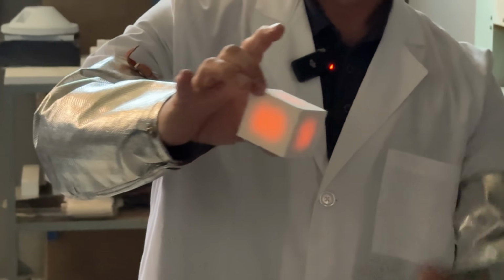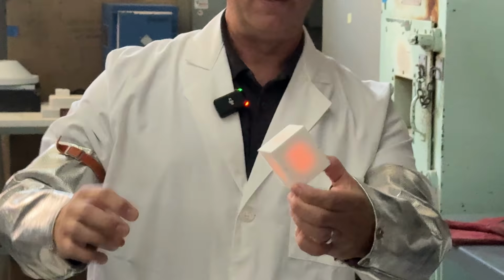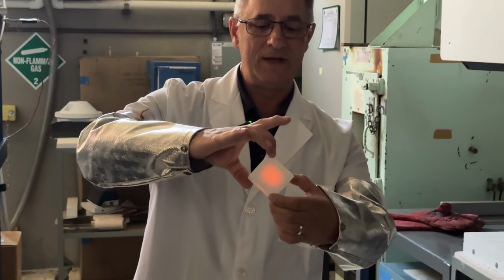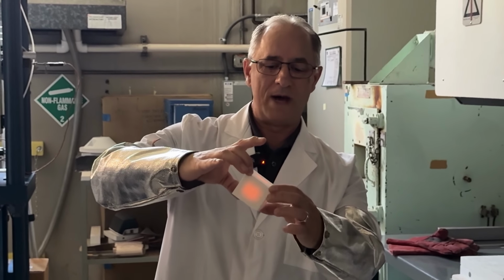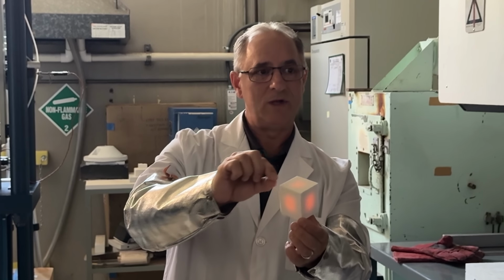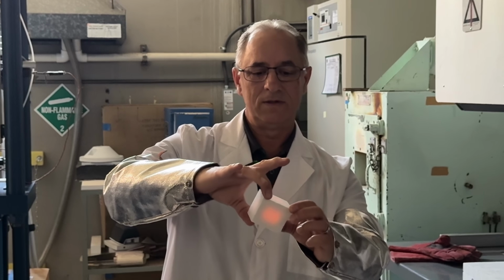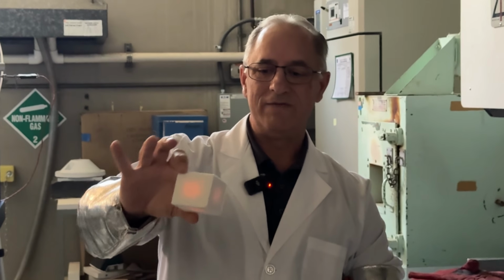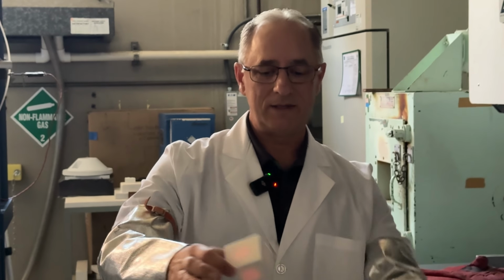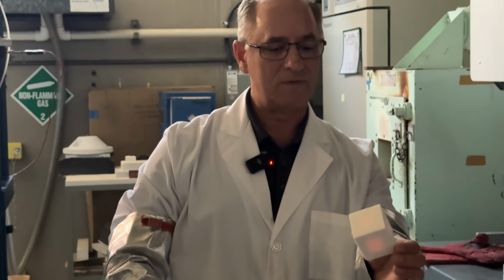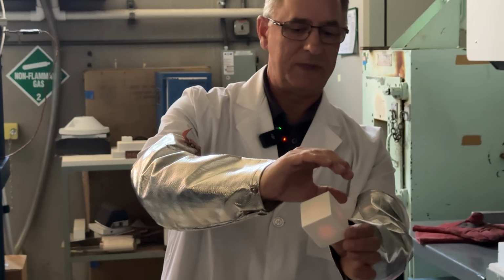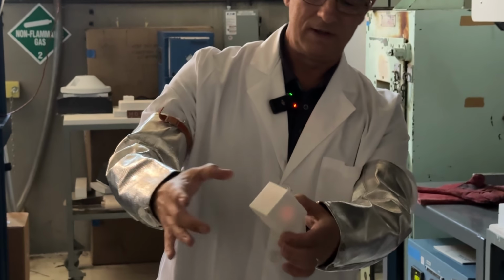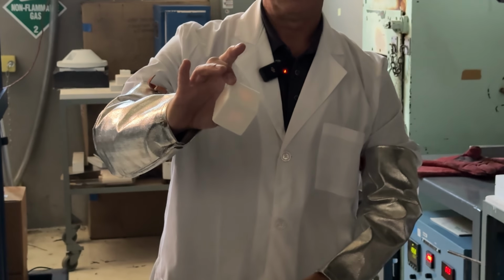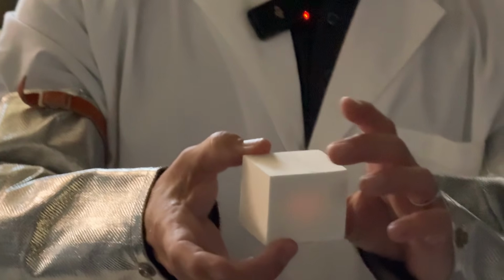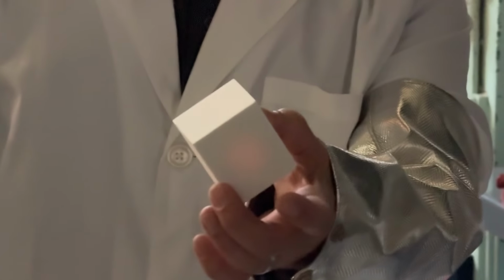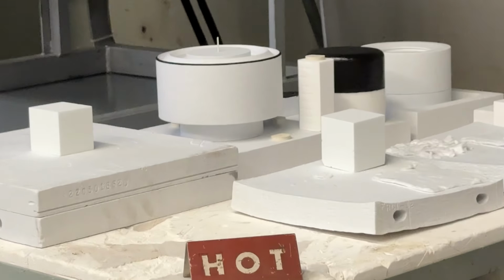The reason why you can pick up these heat shield tiles straight out of the oven is because they have such low thermal conductivity. As soon as they come out of the oven, the outer layers cool just enough that you can touch them, but then the heat from the inside doesn't flow out quickly enough to burn your skin. And of course you can still see it red hot. That's because it's getting rid of heat via black body radiation. That's the reason why you end up swapping the block from one hand to the other, because of the heat radiating out of this, rather than the heat conducting through your fingers, because there's basically no thermal conductivity.